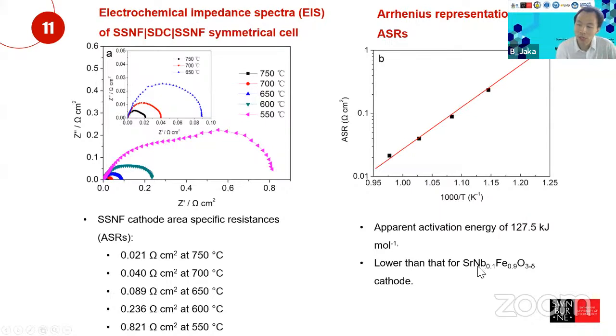So this means that in the SSNF cathode, we are only doping with one dopant, which is the niobium. So when we also add scandium into this B site, or what we say if we introduce a double dopant into the B site, we can reduce the activation energy. The activation energy in here implies the thermal activation nature of a particular material.